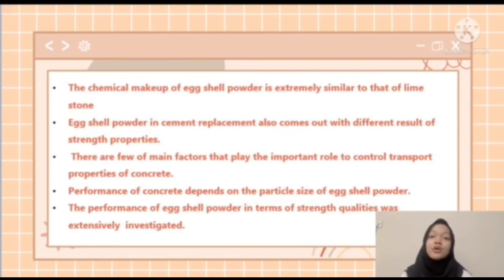Point 3: there are a few main factors that play an important role in controlling transport properties of concrete, which are the volume of paste matrix, the pore structure of the bulk matrix, and the interfacial zone around the aggregate particles. Point 4: performance of concrete depends on the particle size of eggshell powder. It can improve the performance of concrete if the particle size of fine aggregates like eggshell powder becomes smaller, to ensure faster interaction with the other components of concrete, as reducing a material's size increases its reactivity.